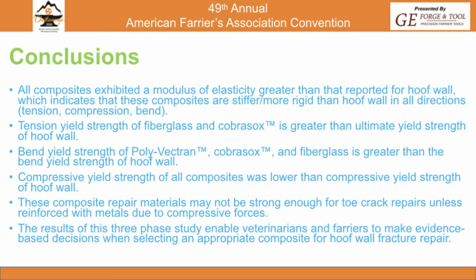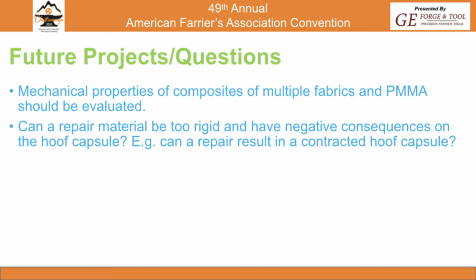These composite repair materials may not be strong enough for the toe cracks unless they're reinforced with metals. And again, I really think it's just from the compressive nature of the proximal end of the toe crack. And the results of this three-phase study do enable vets and farriers now to make evidence-based decisions when selecting the appropriate composite for hoof wall fracture repair when looking at these four. But obviously it does lead us to the future and some more future projects or questions.